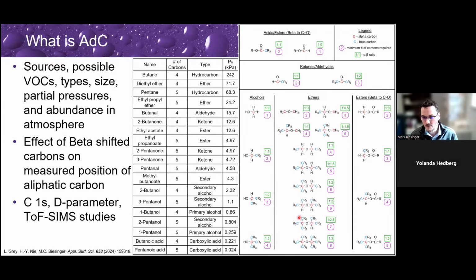carbon? If we look at this carbon here, it is directly bound to an oxygen. That's our primary. It's going to shift the binding energy position of that carbon up around 1.5 eV from the standard alkyl position. These three here look like they're alkyl, but they're actually not. They're alkyl that have a shift to them because of the effect through this carbon to here, and they're going to shift up 0.1, 0.2 eV. So this is not alkyl carbon, this is a beta shifted alkyl carbon. And that's adding error to the position of where that alkyl peak is using our standard fitting.